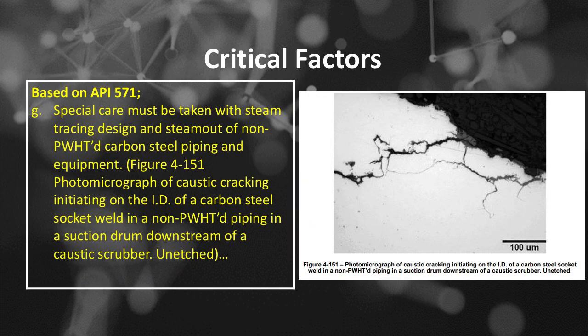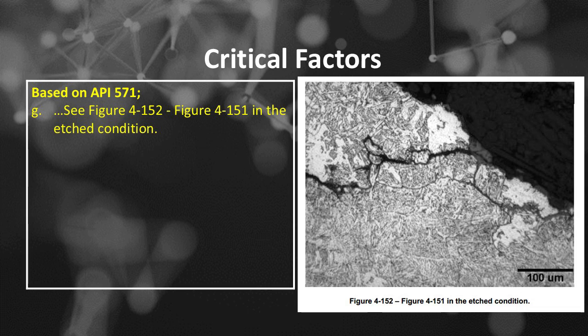Number G, special care must be taken with steam tracing design and steam out of non-PWHT'd carbon steel piping and equipment. See Figure 4-151, photomicrograph of caustic cracking initiating on the ID of a carbon steel socket weld in non-PWHT'd piping in a suction drum downstream of a caustic scrubber. Unetched. See Figure 4-152, Figure 4-151 in the etched condition.